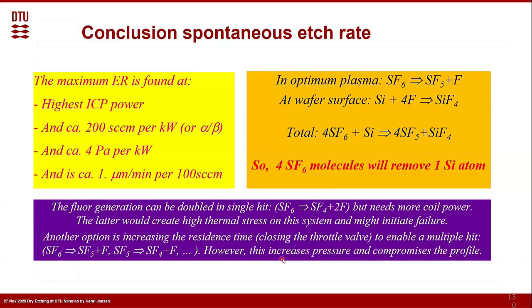And this maybe would be a nice way. But of course, when you go to the higher pressure, we will see that directly, then your ion angular distribution is going to be compromised. So it could be that your profile becomes not as nicely straight anymore. But it's good to know that you can be more sustainable and use your gas in a much better, more efficient way when you increase the pressure or increase the residence time.